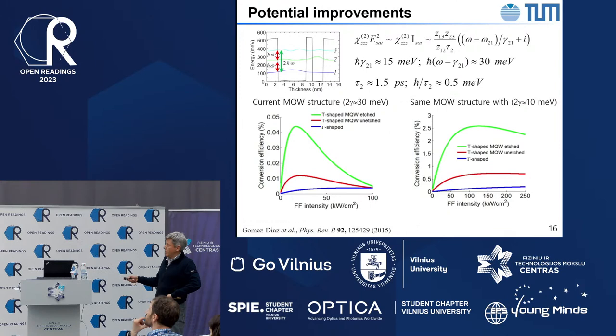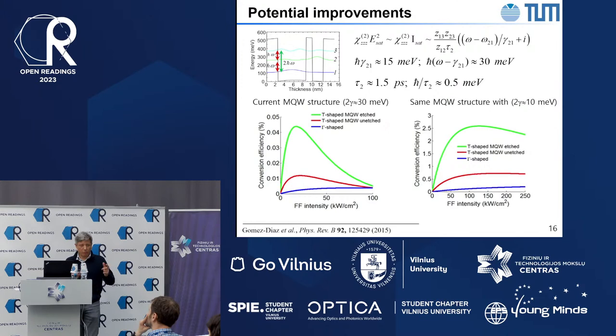and theoretically in this model it was actually even a bit lower than what we experimentally observed, but order of magnitude roughly there. The same model predicts that if we manage to improve our growth quality, which reduces the line widths of these intersubband transitions, ideally, fundamentally, the line width is really limited by only a few millielectron volts, by phonon scattering and other fundamental materials. But the 30 millielectron volts that we have in our actual structures is really the growth quality, and potentially it can be improved. So even the smallest improvement here already could lead to significant enhancement of the conversion efficiency before the saturation, moving to a few percent. And that means that the metasurfaces potentially could be a practical nonlinear optical element that would allow converting mid-IR frequencies from one to another.